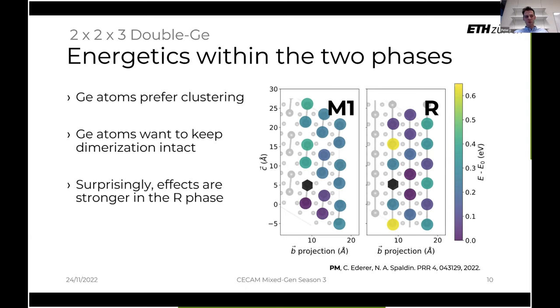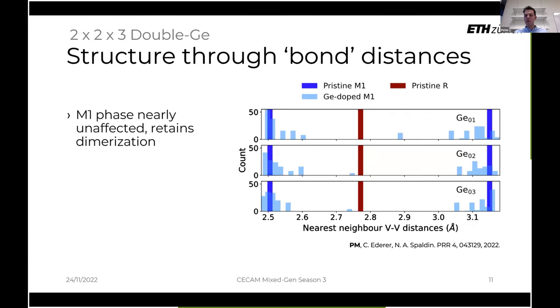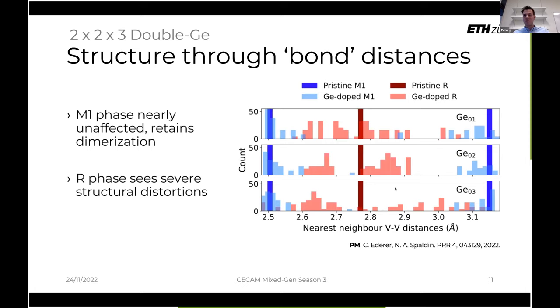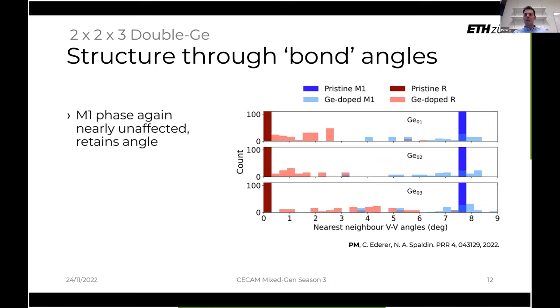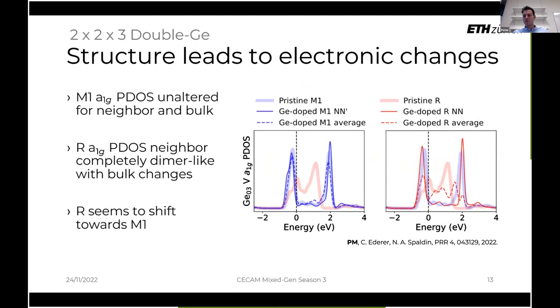And then getting into answering the question. So yes, of course, we're not really able to say with certainty that it is not just the disorder of the rutile phase that makes it insulating in some new, let's say, more exotic way. But from the way we see the structure changing, from these plots that are shown here, we only see that the distances get a bit disordered. We also see that the angles get a bit more disordered. But if you look at the electronics, the density of states, as I'm showing here, I think we can really see that some of the vanadiums near the germanium, so if we really have germaniums that push vanadiums next to each other, we do see some sort of singlet forming, let's say, or a strong antibonding feature, which is in very nice agreement with the monoclinic phase.